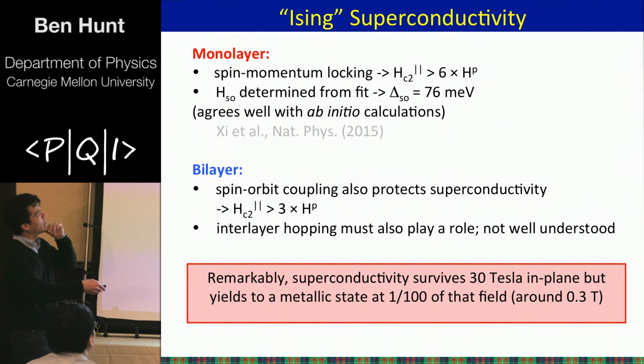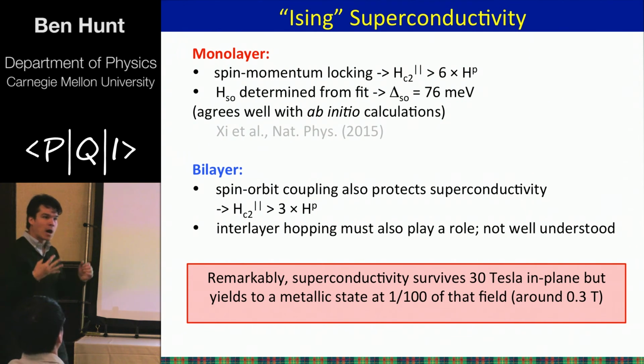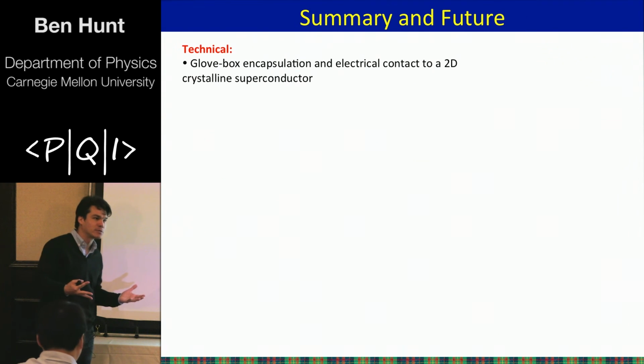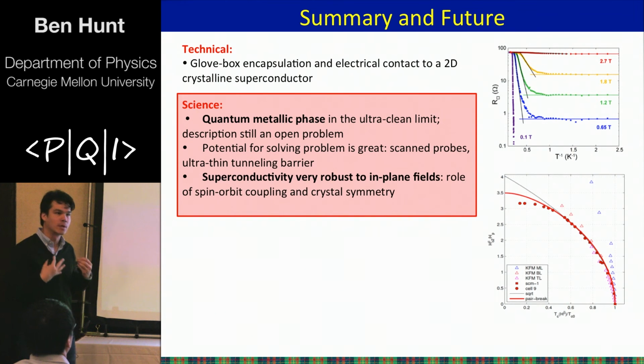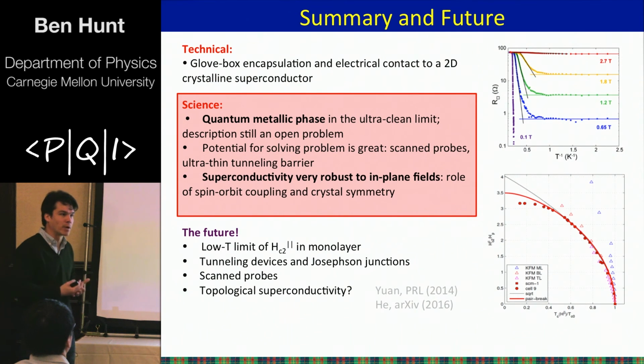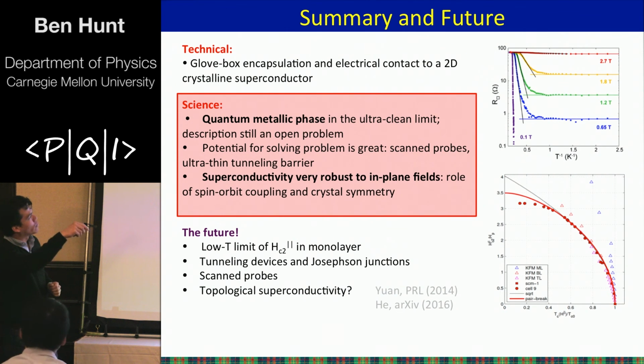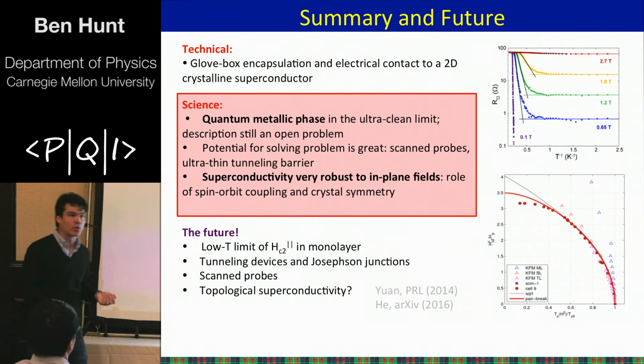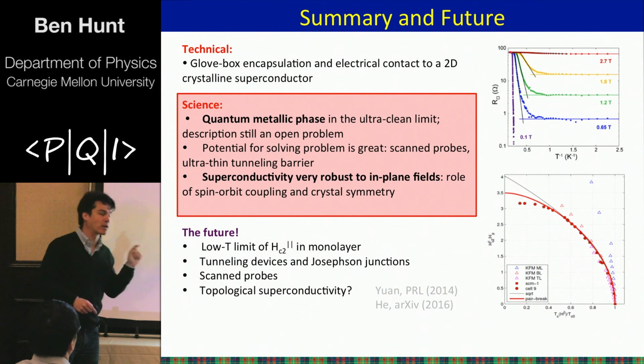Let me just summarize my talk. From a technical point of view, a really good way of making 2D superconductors is to do it in this glove box. Otherwise, they oxidize and they disappear. So we can use our van der Waals techniques to build up heterostructures of 2D superconductors and metals or whatever, or interfaces between superconductors and semiconductors. From a scientific point of view, we rediscovered this quantum metallic phase in the ultra-clean limit, a very low disorder system. And we also showed that superconductivity is very robust to in-plane magnetic fields.